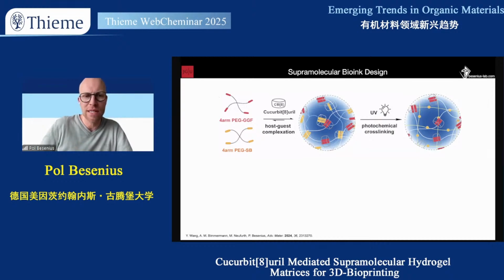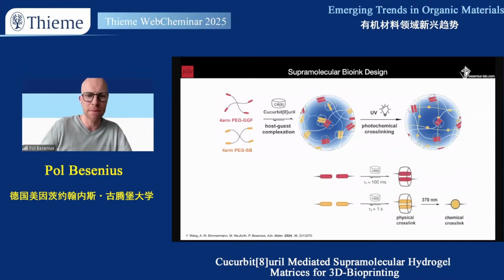We use GGF, so glycine-glycine-phenylalanine motifs, which like to bind, and the other unit that we like to use is a stilbazolium unit, for reasons that are also already shown on this slide, because this then becomes light responsive, and we can do a stepwise processing of this hydrogel matrix. These are determined by the on-off rate of that supramolecular bond, and this is something we can determine by doing shear rheology of the hydrogels when they are produced. If you take a tripeptide glycine-glycine-phenylalanine homoternary complex in the cavity of CB8, the lifetime of the bond is about 100 milliseconds. For the stilbazolium unit, as you will see soon, it's about an order of magnitude more robust in terms of kinetics, not in terms of thermodynamics, but in terms of kinetics.